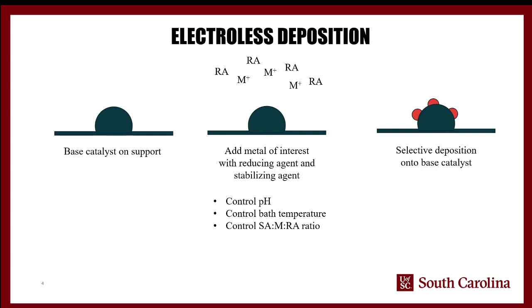And one of the things that the Monnier group has done is they've demonstrated that they can use syringe pumps to continuously inject the reaction solutions into the chemical bath. And in doing so, they're able to dictate exactly how big the particles are going to be. It follows pretty intuitively that the more reactants that you add, the more metal is going to be reduced, and thus the bigger the particles are going to be. And so by controlling both the amount and the speed at which the reaction solutions are mixed together, they can very precisely control the rate of deposition and thus the size of the particles.